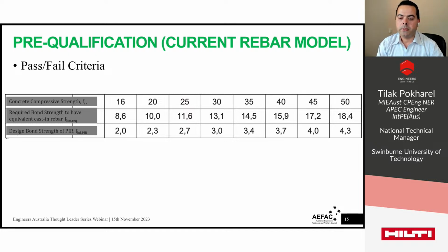For simplicity, let's pick one concrete grade and look into the detail. Here, I've chosen the 20 megapascal concrete, as highlighted in green on the screen. The bond strength of the post-install reinforcing bar is calculated from the experiment in accordance with the EAD I mentioned earlier. So if the bond strength from the experiment is higher than 10 megapascal, the design bond strength is taken as 2.3 megapascal. Okay, so if the test value is 10 megapascal, the design value would be 2.3. So there is a large safety margin here.